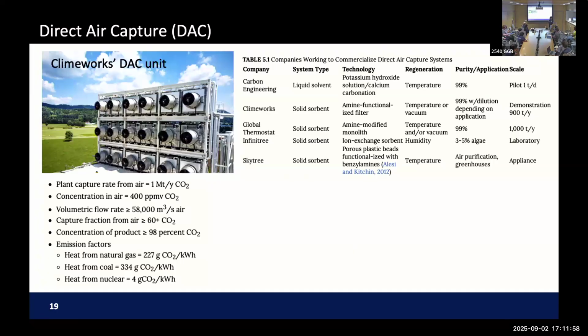So one thing we know is that, for example, my group has been working on microwave reactor, next generation of it. Definitely, we can release CO2 instead of half an hour to an hour, within a couple of minutes, all the CO2 comes out. And surface temperature of particle or fiber remains very cool. It's about 50 to 60 degrees C, but we still don't have a method to measure molecular level temperature difference. I think that where carbamate is, it's much higher temperature, but I don't know how to measure that, right? So that's another challenge, but we're just guessing that. So we know kinetic is much faster. We are targeting heating and all good.